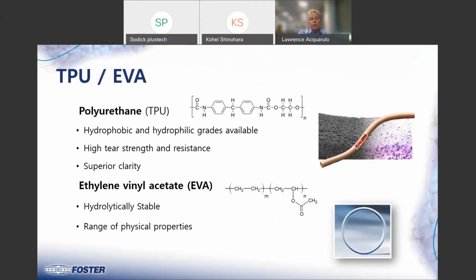Polyurethanes could be rigid, but mostly are flexible, and they could be hydrophilic, meaning absorbing liquids and moisture, or hydrophobic. Very good tear resistance, strength, and used in a lot of catheters and tubes that are left inside the body, but also certain mechanical devices that require some flex. But again, you don't want to stress crack over a period of time. So there's a range of these polyurethanes that have been tested, and again, a good proven track record.